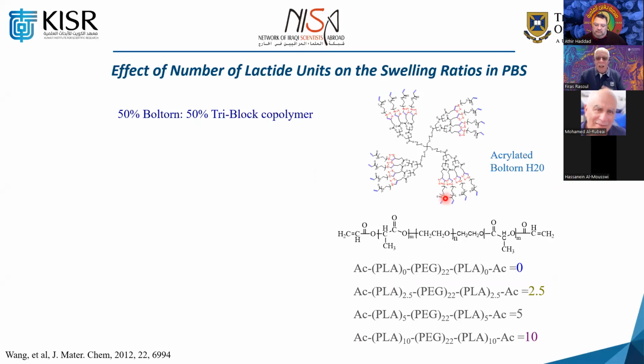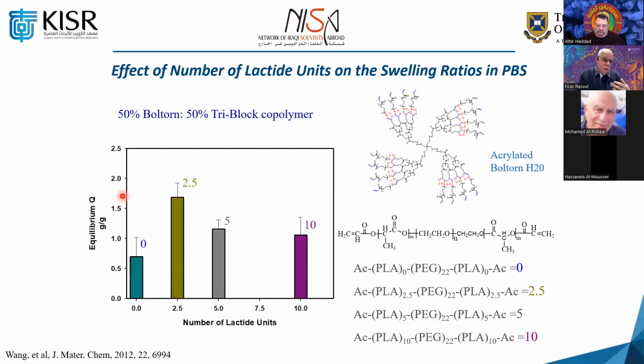So this is what we did. We synthesized a variety of compositions, 50-50, with the tri-block copolymer. This is the one. We used zero lactide, as you see, zero polylactic acid on both sides. It is only pure polyethylene glycol, 22 repeated units. We used it with 2.5 units from both ends. We used it with 5 units on both ends. We used it with 10 units on both ends in order to see which one is better for us with regard to equilibrium swelling rates. You see, this is the zero. It doesn't have any polylactic acid.